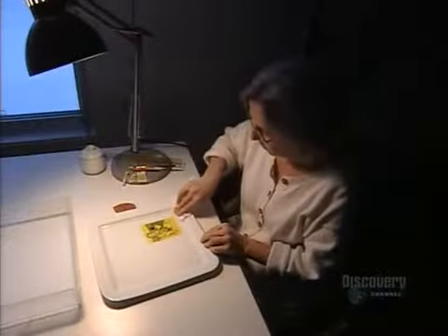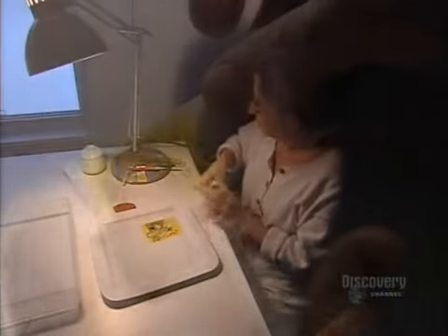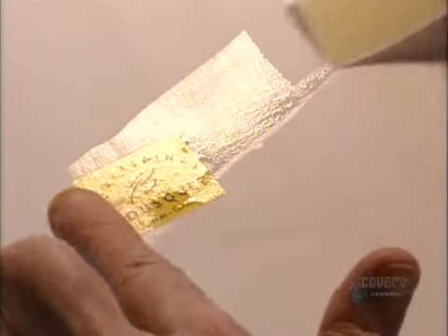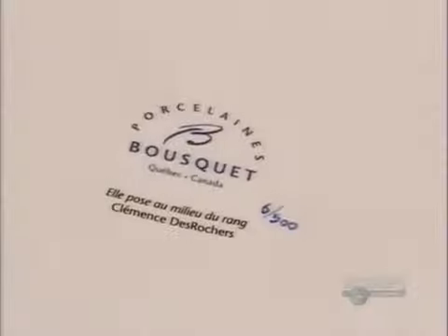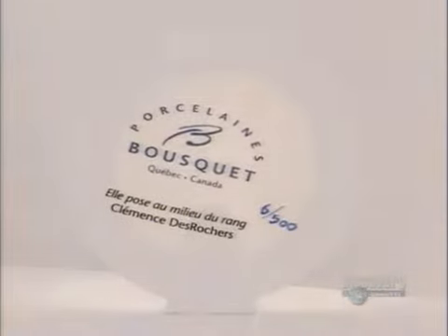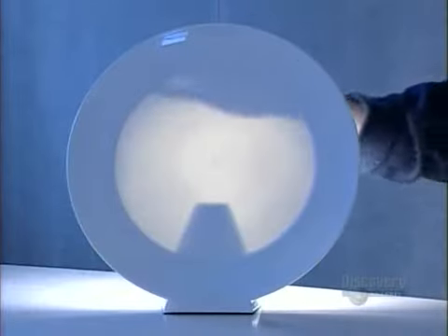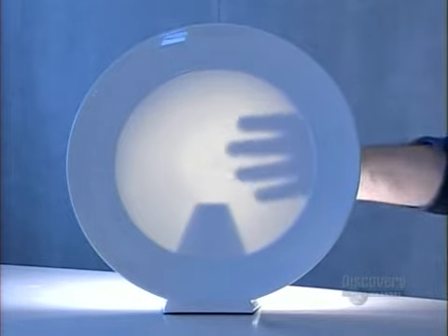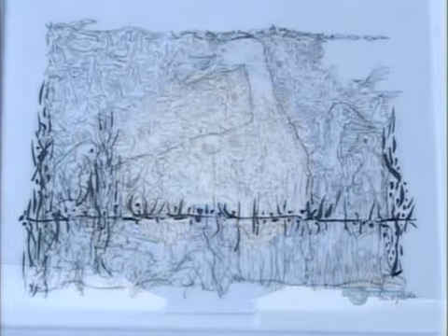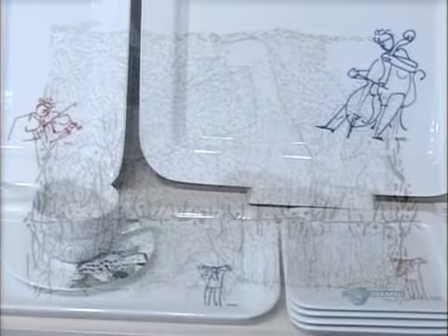After a quality check, a craftsman applies the company logo with a transfer decal. The logo melts in when the plate goes back in the kiln for another 12 hours at 850 degrees Celsius. In the end, the porcelain is translucent enough for light to shine right through. Other pieces offer more illustrated displays for a truly fine dining experience.